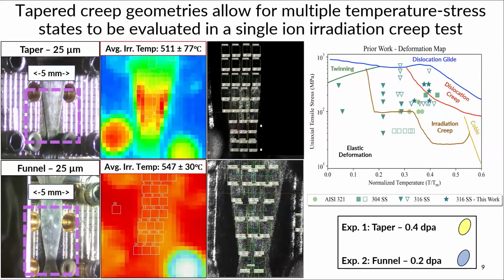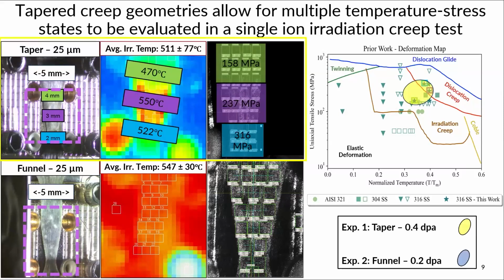So I have two experiments that I'm going to talk about. The purple dashed line is our beam area. The first experiment was our first taper one with an average temperature of 511 with a significant variation of 77 degrees C. That's our IR camera in the middle, and then the strain tracking on the far right. The bottom right shows a much better picture of the speckle pattern that is created from our laser speckle extensometer. And then I plotted my contributions to the deformation map, and you'll see that they popped up on the right.